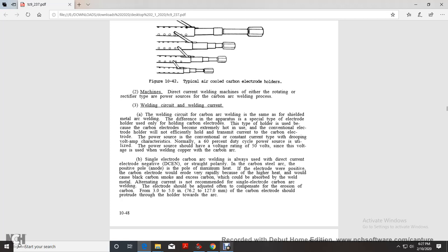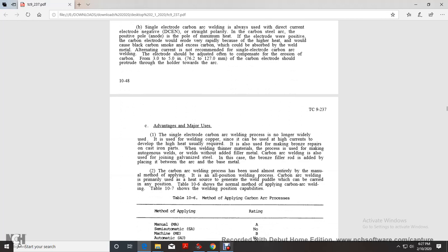Single electrode carbon arc welding is always used with direct current, electrode negative, straight polarity. With the carbon electrode positive, the positive pole would have the maximum heat, and the carbon electrode would erode very rapidly because of the higher heat, producing black carbon smoke with excessive carbon which could be absorbed by the weld metal. Alternating current is not recommended with single carbon arc welding. The electrode should be adjusted to compensate for the erosion of the carbon: from 3 to 5 inches of the carbon electrode should protrude through the holder towards the arc.